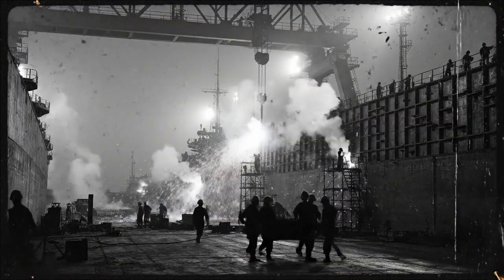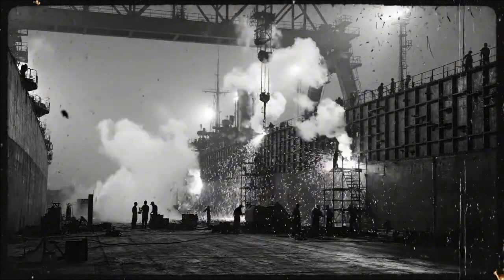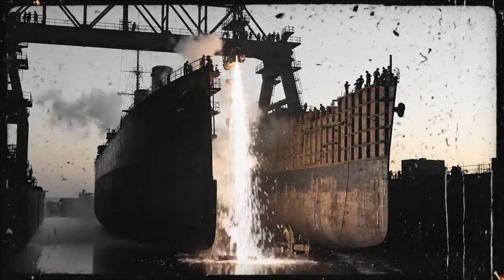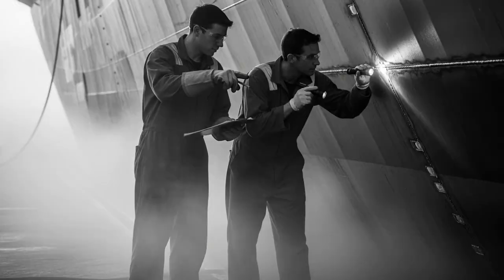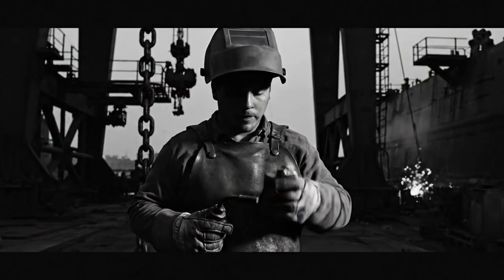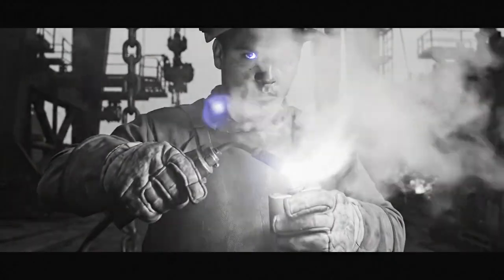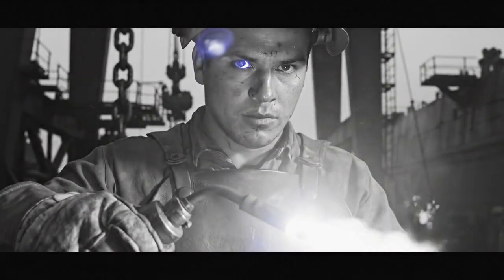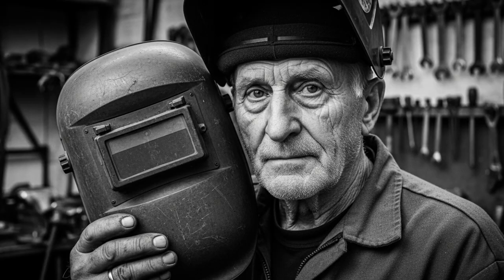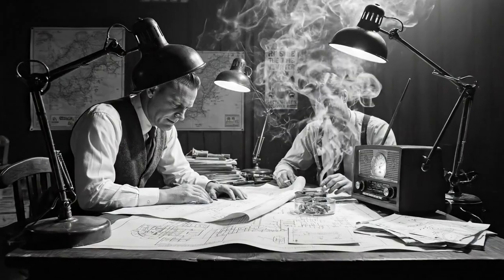July 15th, 1942. USS Patrick Henry, Dry Dock Number 7. A newly completed Liberty ship is undergoing pressure tests before delivery to the Navy. At 800 hours, water begins leaking from a seam on the port side midship. The leak is identified as a cold joint, a weld that did not properly fuse the 2 steel plates. The welder who performed this work is a 19-year-old farm boy named Robert Schultz. He had been welding for 9 days. The weld was executed at 300 hours in sub-freezing ambient temperature. The steel was cold, he did not preheat it.